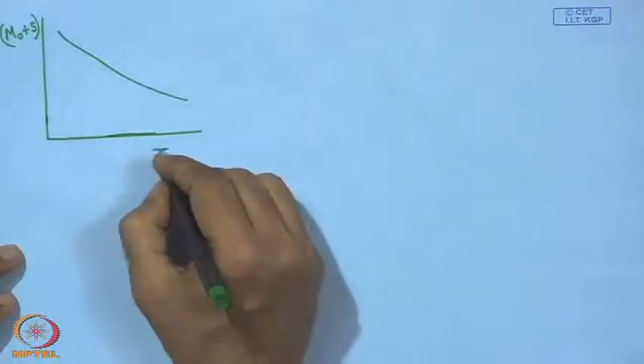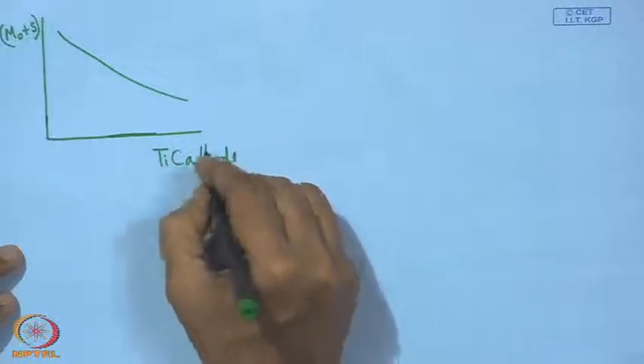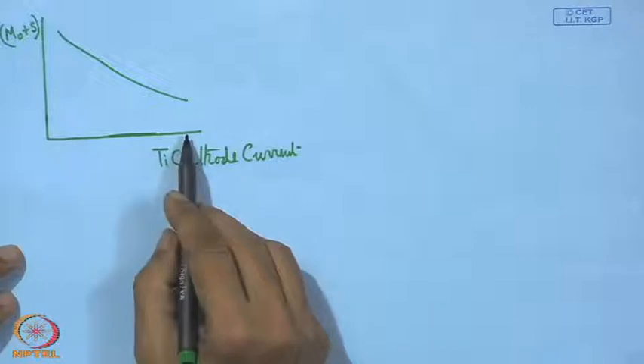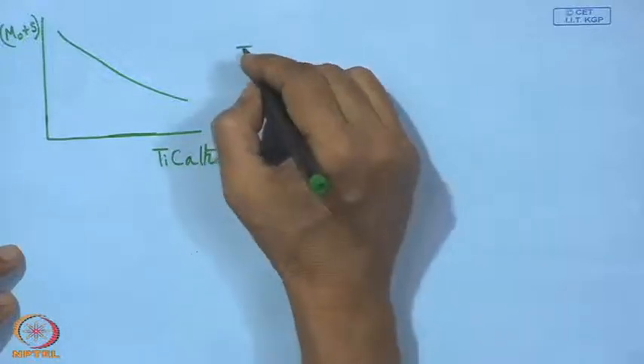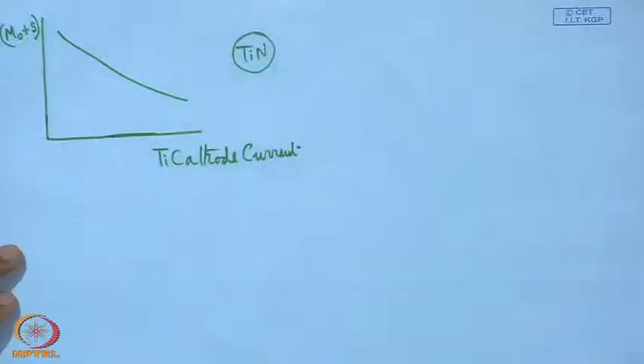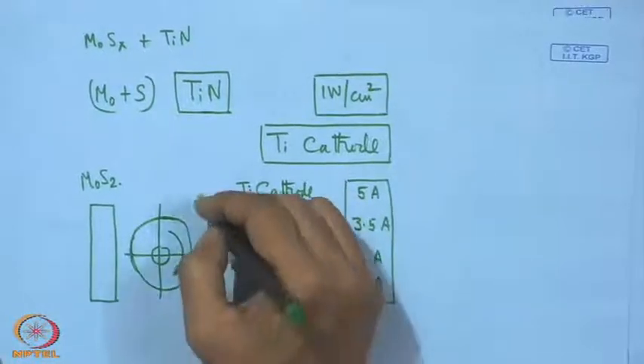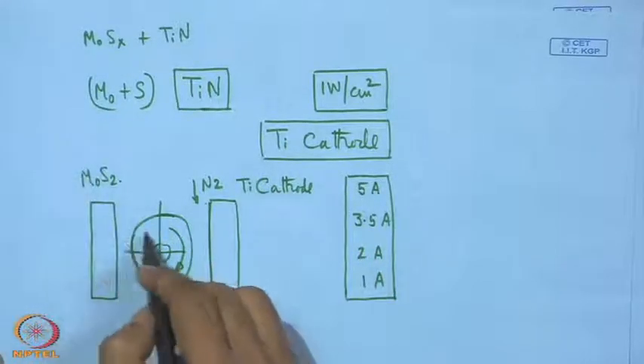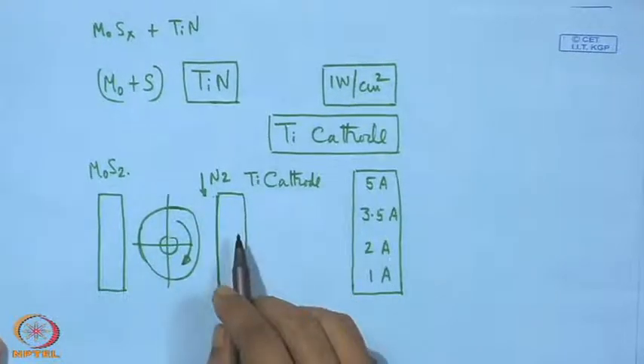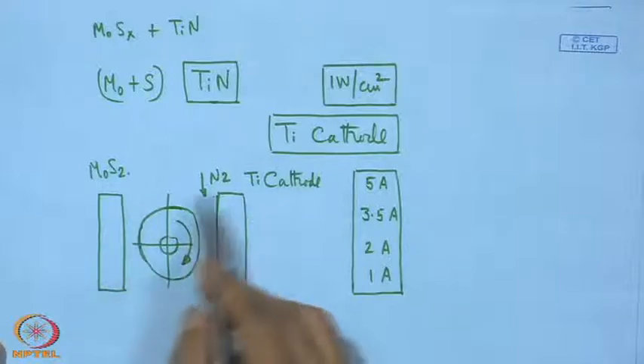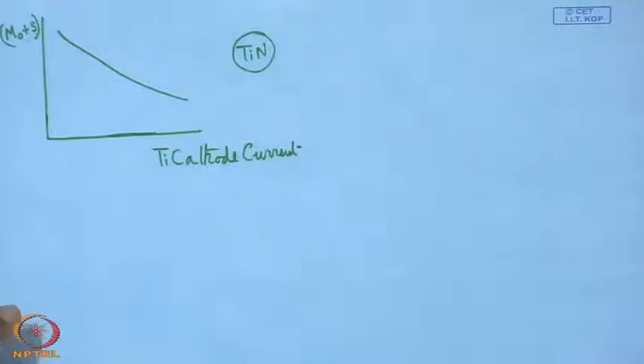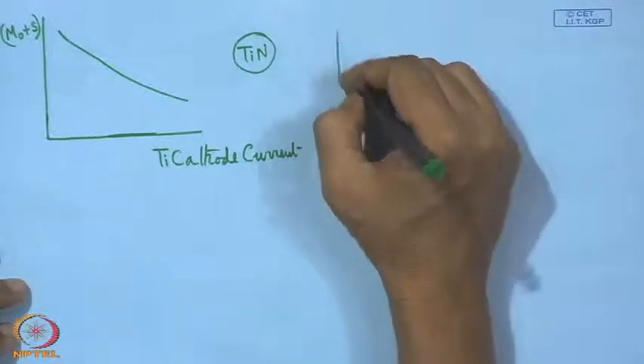So, what we get is something like this. It is titanium cathode current versus percentage of MoS. When we have a higher value of titanium, naturally we have a higher percentage of titanium nitride in the coating. This is actually a reactive sputtering, where titanium and nitrogen admission gives titanium nitride, and then MoS2 as a whole is deposited. So, it is a reactive sputtering of titanium nitride and direct sputtering of MoS2 using a pulse DC system. And we have another observation in this case, that is the S by Mo ratio.